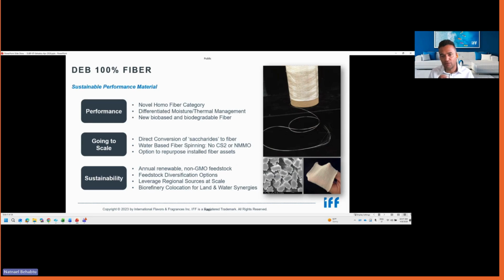The other thing that I want to leave you as a message about this technology is, again, in its water-insoluble version, this alpha-1,3 material can be a fiber-forming polymer. You see here actual fibers that we've spun. This is the cross-section. This animal cracker-like structure is reminiscent of viscose fiber, and this is a woven structure created 100% by this alpha-1,3 polymer. So we are able to create a novel homofiber category. I'll show you in the next slide how it has a unique behavior when it comes to moisture and thermal management. It's bio-based and biodegradable. It's a polysaccharide, right? So it's not surprising that the material has this behavior.